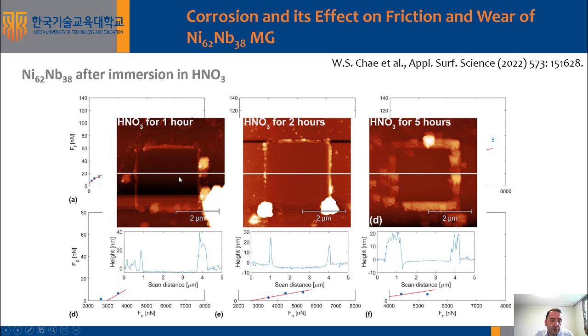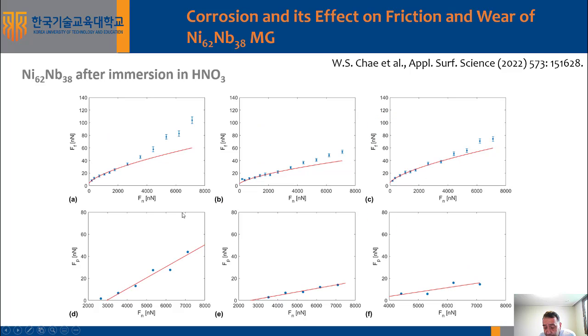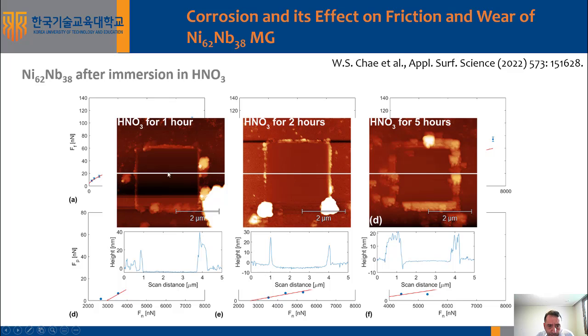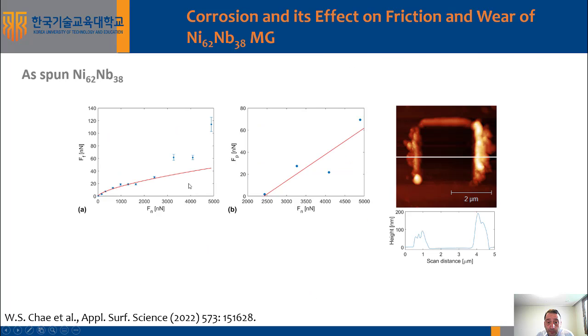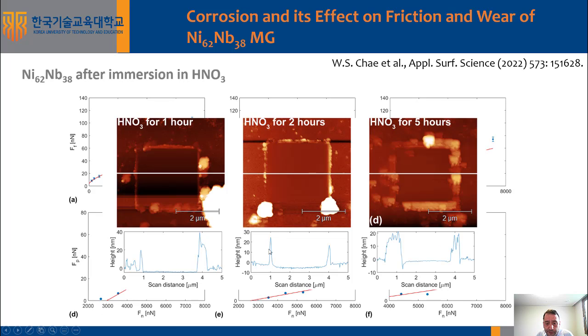So this is also confirmed by imaging the surface after scratching on these alloys, where we find now that the amount of pileups, or the height of the pileups, is much smaller than before immersion into acid, where we had pileups that went as high as 200 nanometers, while after immersion into nitric acid, the pileups are only in the range of up to 30-40 nanometers.